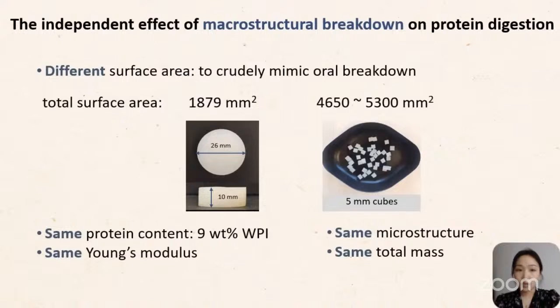We also studied the independent effect of macrostructural breakdown. We simply cut the gel cylinders into many small gel cubes to roughly mimic the oral breakdown. And the only difference between the gels is the total surface area caused by cutting.